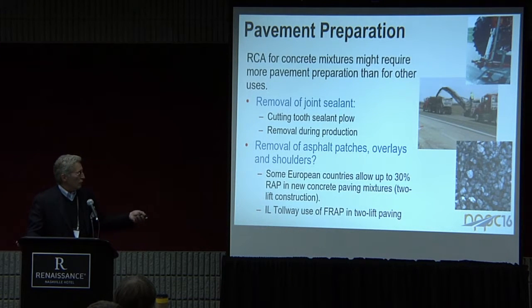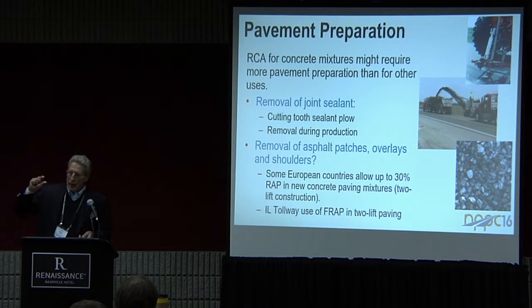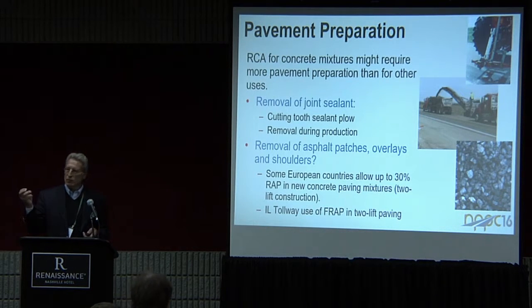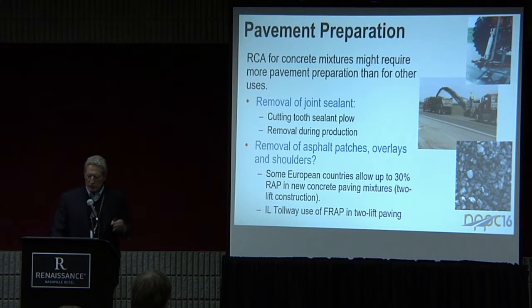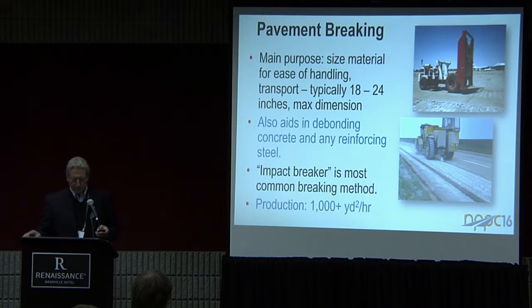particularly in two-lift construction. And Illinois Tollway, for example, is actually specifying and allowing the use of what they call fractionated recycled asphalt paving. It's the coarser asphalt particles. They're taking the fine stuff, which has got the higher asphalt content, using that back into asphalt applications, but the coarser particles, they're putting that back into the lower lift of two-lift paving, along with, if the contractor desires, crushed concrete aggregate as well. So lots of use of recycled materials that way.